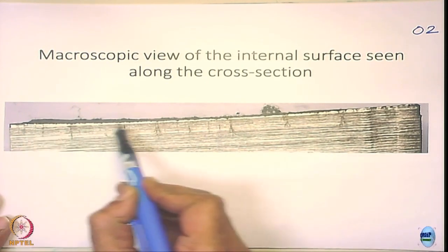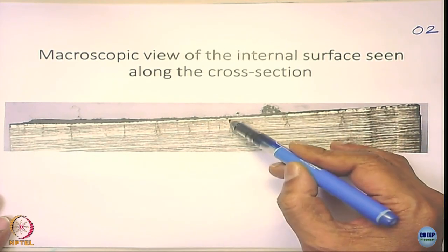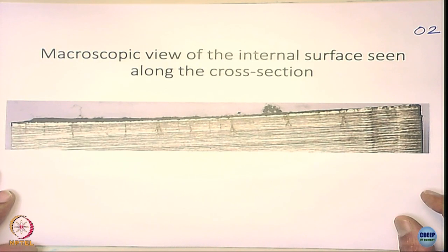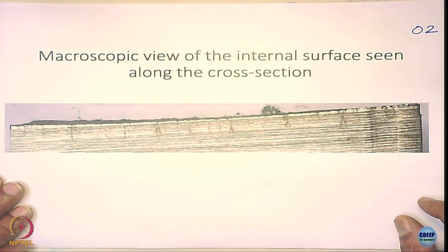So, the problem in stress corrosion cracking is that it can cause a premature failure, and certainly it is not going to cause too much corrosion. See here the surface, internally, and you do not really see much corrosion at all. Wherever a crack happened and subsequent places, you are not seeing any corrosion. So, visually they are not undergoing severe uniform corrosion at all. This corrosion is very localized and is called stress corrosion cracking.